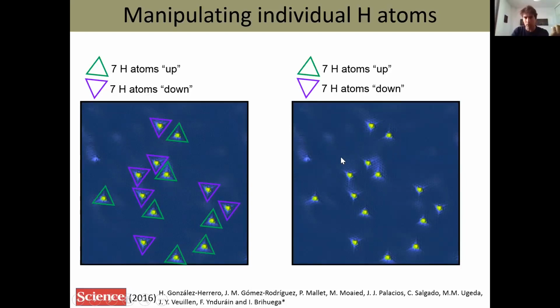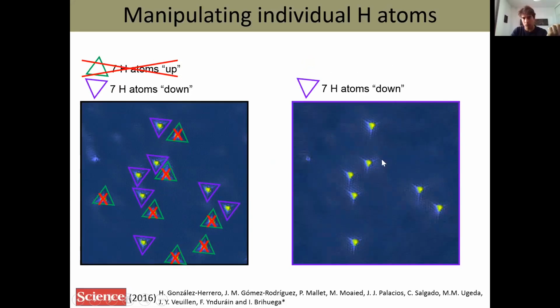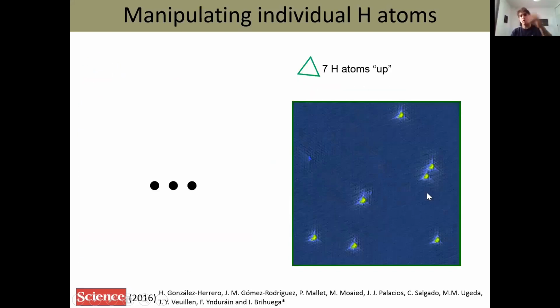But now we can go with the tip and we can remove all the hydrogen atoms from one of the sublattices, and this is what we do. Okay, we have 7 and 7, and now all the hydrogen atoms are in one sublattice. And we can continue with this manipulation and change sublattice. So we can really manipulate hydrogen atoms and decide where we induce magnetic moments.